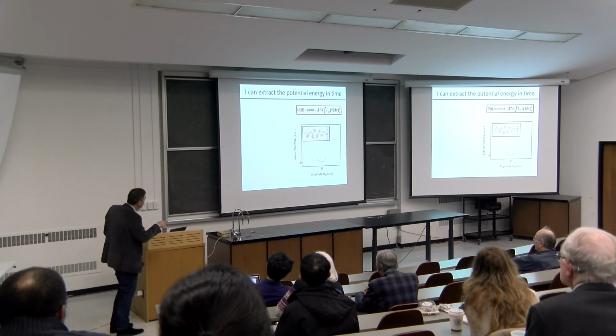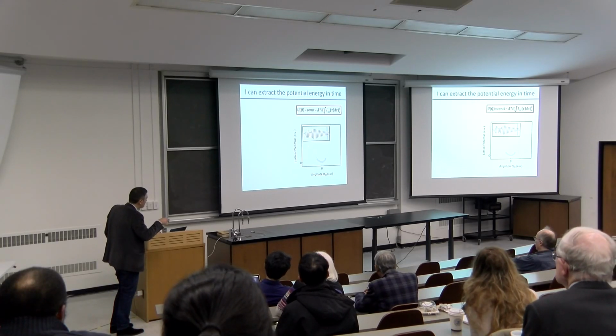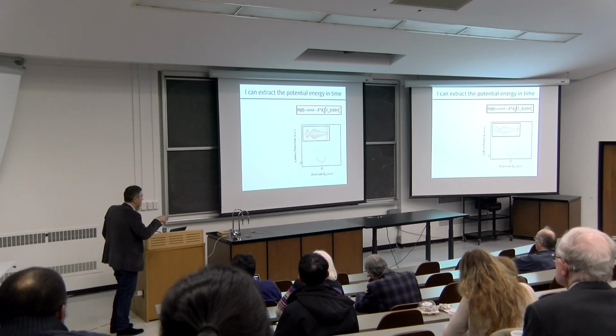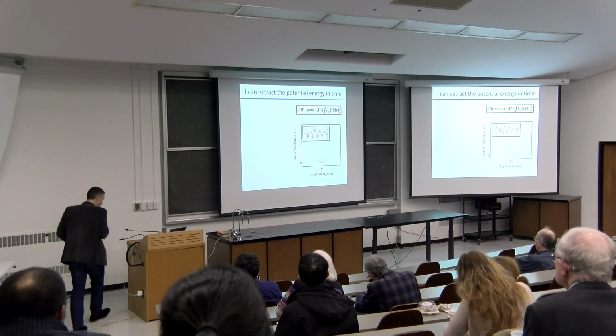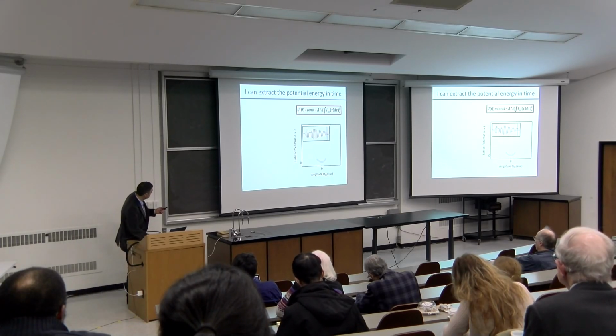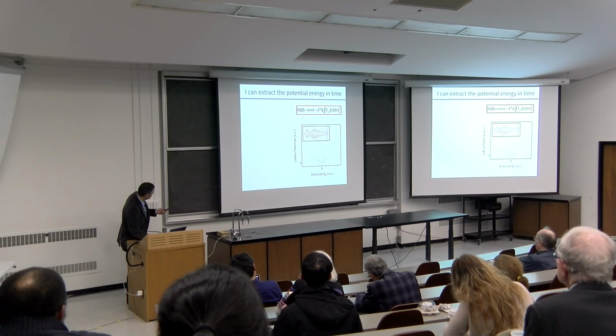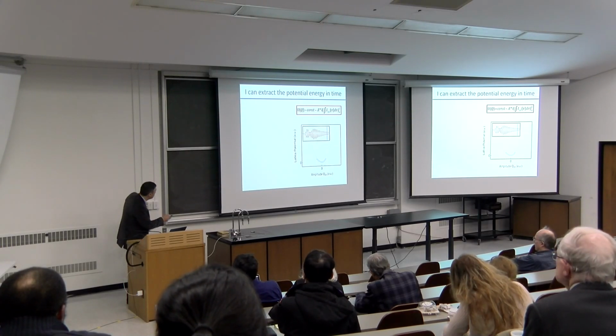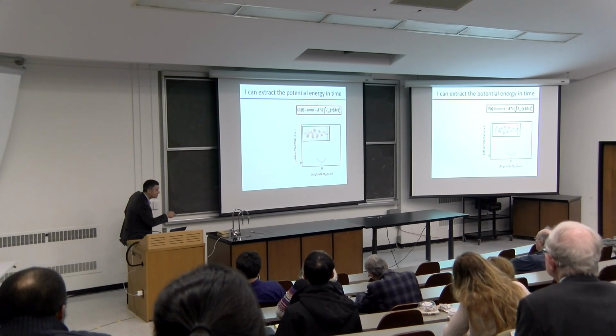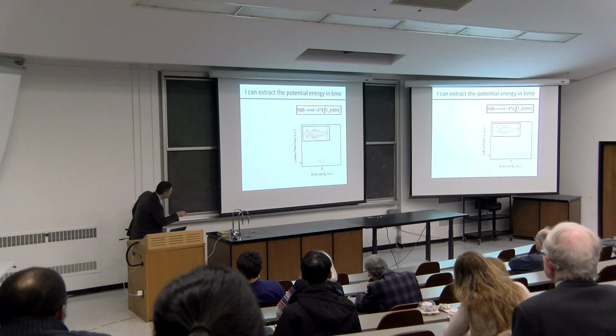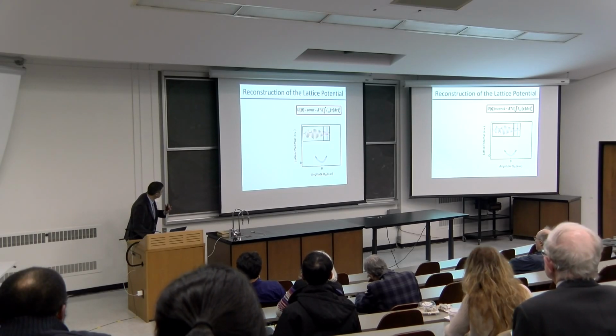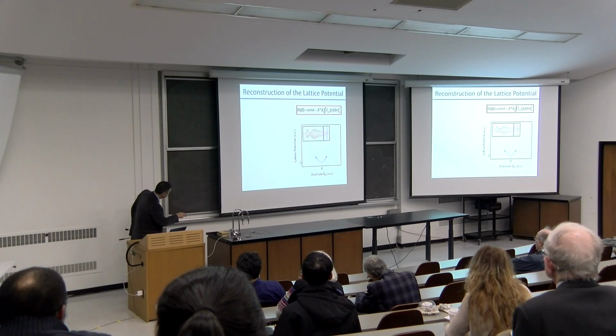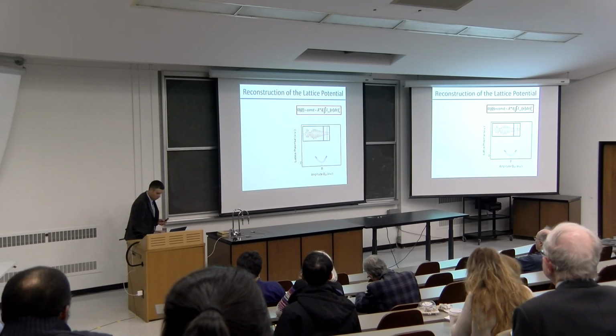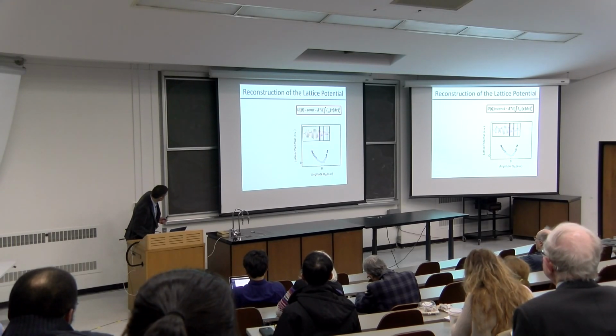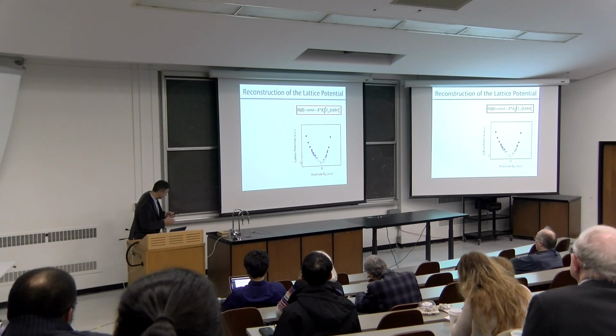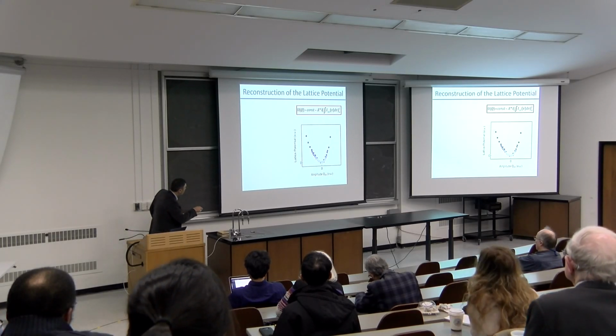Okay, so at each one of these cycles, my phonon will be exploring the interatomic potential in this way. So now I'm at far delayed times where, because the total energy of the phonon is small, I'm only exploring a small excursion. But then now I come earlier in time, and that's good because I'm exploring the same, and then I'm seeing a little more. And then earlier in time, earlier in time. And so what I get is something that is a measure of the interatomic potential.